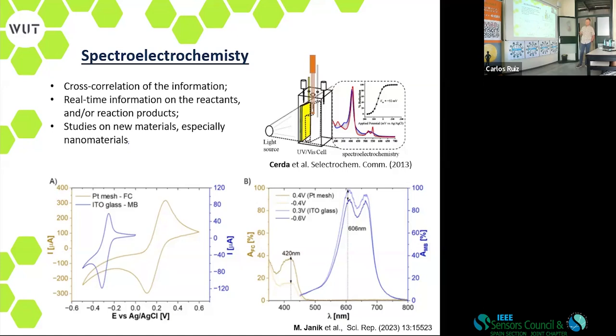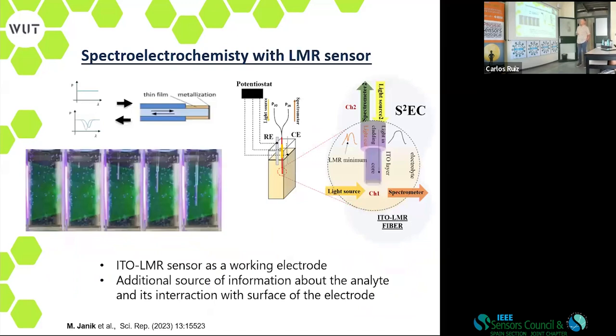So these are different electrolytes that we use. You can see that these peaks appear different in different probes, different electrode materials, but these are also optical. So you can see that the transmission changes differently depending on electrolyte and applied voltage. So why not use the fiber instead? It's smaller, it may be quite effective, and it does not disturb the change in optical path.